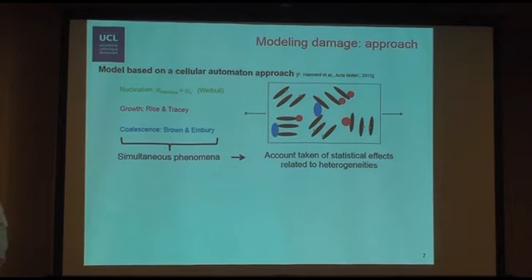It is directly linked to the unit cell calculations, because even if not coupled, we use the results of the plasticity calculations as an input for the modeling of damage, for which we use a cellular automata approach. The power of a cellular automaton is that it makes it possible to account for the statistical aspects related to the different possible heterogeneities of the microstructure. And those heterogeneities in the model are the parameters of the plasticity calculations, so morphology, orientation, martensite volume fraction, and martensite carbon content.